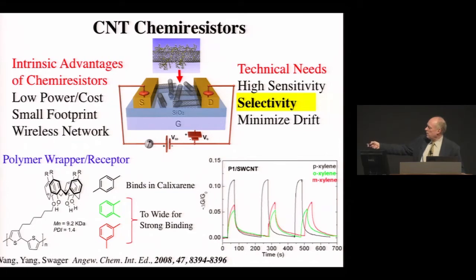The one that has the methyls on the two termini is kind of longer and skinnier, and it fits very nicely in this bucket. We determined binding constants in solution of this, but the ortho and meta versions of this do not fit nearly as nicely, so they don't bind as well. Now it turns out this corona here, the xylenes also can kind of solvate that. They can kind of swell it, so you have some non-specific interactions, but then you have the specific interactions.